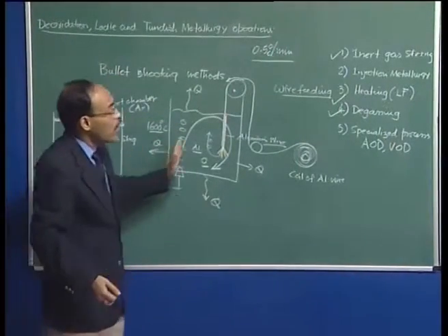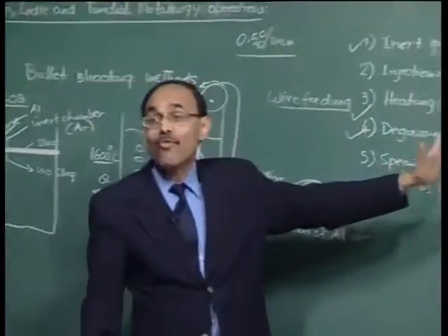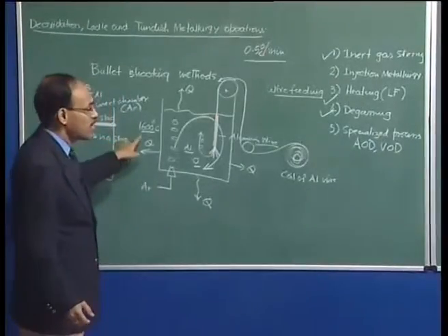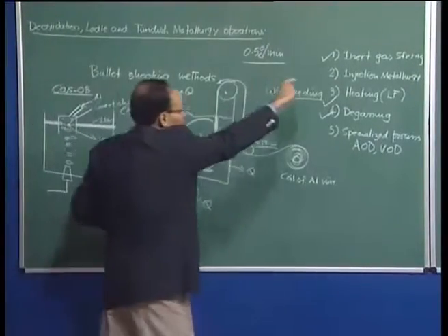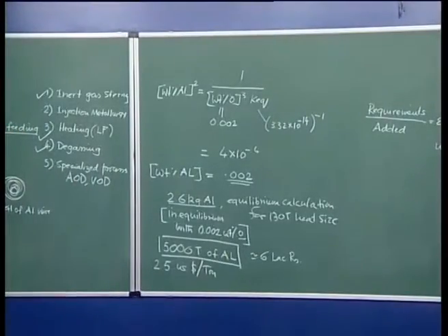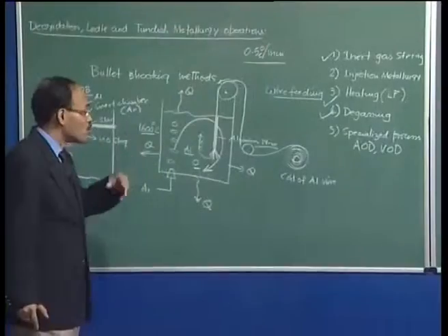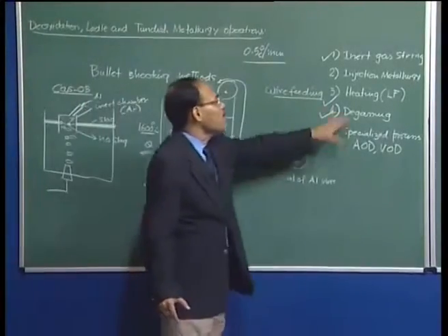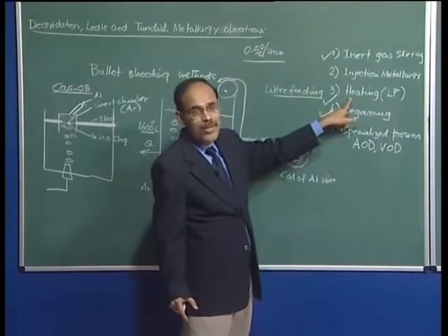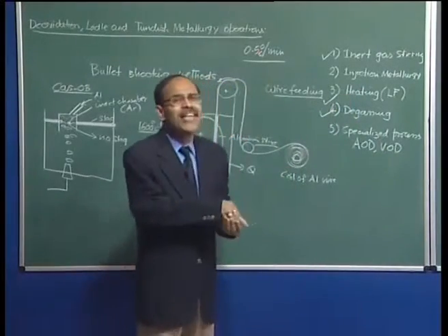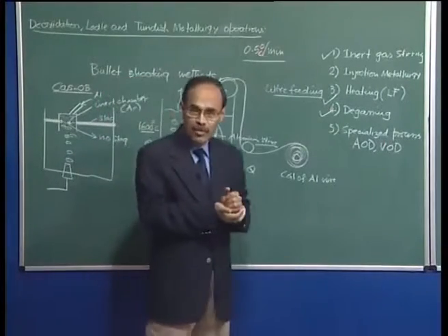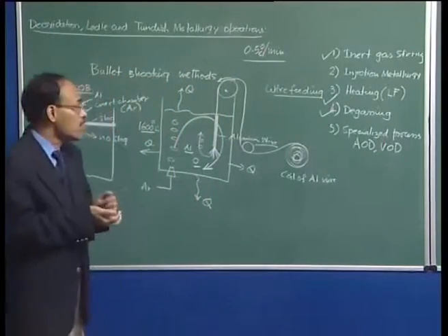But remember that the downstream process is the continuous casting process, where we require a fixed temperature. So, we have tapped the molten metal at 1600 degree centigrade. If you do not do heating and carry out all these operations, by the time the material goes to the continuous casting bay, it is going to be considerably chilled, maybe prematurely solidify as well. So, somewhere in between the circuitry of ladle metallurgy, we do require that a heating operation be done, and this heating operation basically compensates for heat loss as well as heat required for many endothermic processes which are carried out under ladle metallurgy steel making conditions.